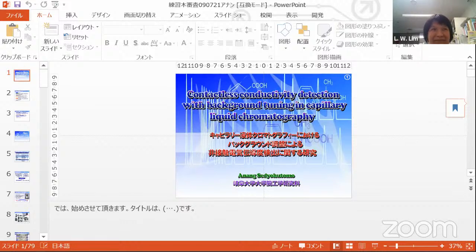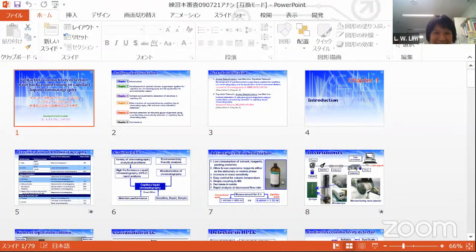At the beginning, we found that the nanoparticles actually got stuck inside the column, and they don't come out no matter what eluent we use. So at the end, we have to wash everything with organic solvent to clean the column. Because of that, we gave up the separation of nanoparticles. But for other particles, micro size and above, usually there's no problem.